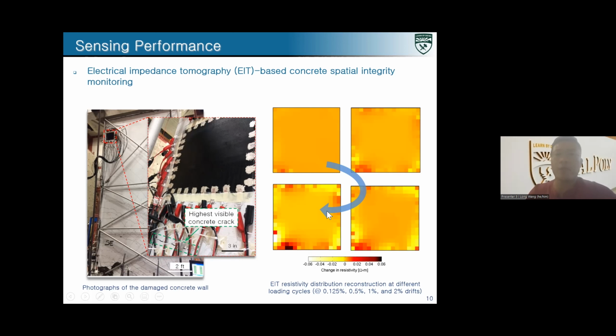This is the electrical imaging algorithm that we use to characterize the electrical property of this sensing material, which can be correlated to the mechanical response of the structure. The highlight is the hotspot that developed at the end of the experiment, which indicates that there could be either non-visible structural damage or stress concentration that can potentially propagate into structural damage.